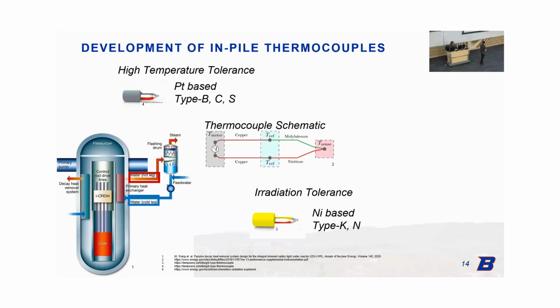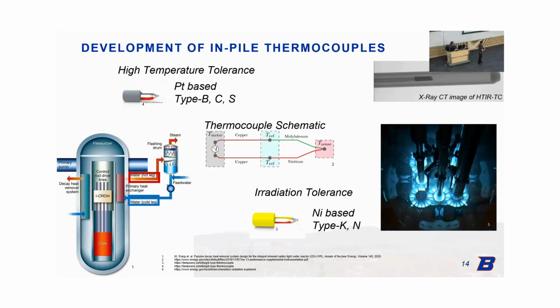So what we wanted to do is design a thermocouple and characterize its stability that combines the high temperature sensing capabilities of the platinum-based types B, C, and S with the irradiation tolerance of types K and N. In doing so, we were able to produce with the Idaho National Lab a thermocouple called a HTIR-TC, which is composed of niobium and molybdenum thermoelements and is actually commercialized at the moment. It also received an R&D 100 award in the year 2019, partially because it holds the record for the highest sustained temperature measured with no measurable drift within a reactor core, which was in the Advanced Test Reactor over at the Idaho National Lab.